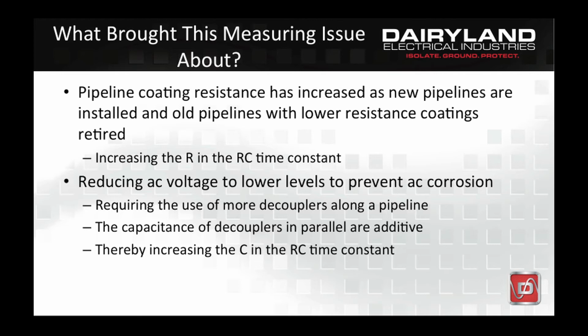A second factor is the recognition in recent years that voltage has to be mitigated to lower levels in low resistivity soils to minimize AC corrosion. This is often done by installing lower resistance AC mitigation grounds and more decouplers along a pipeline that is affected by induced voltage. The capacitance value of the decouplers furnished by Dairyland has been the same since they were initially introduced, so they did not contribute to a change in the circuit RC time constant. But added decouplers in parallel do increase the C in the circuit RC time constant because the capacitance values of decouplers in parallel are directly additive.